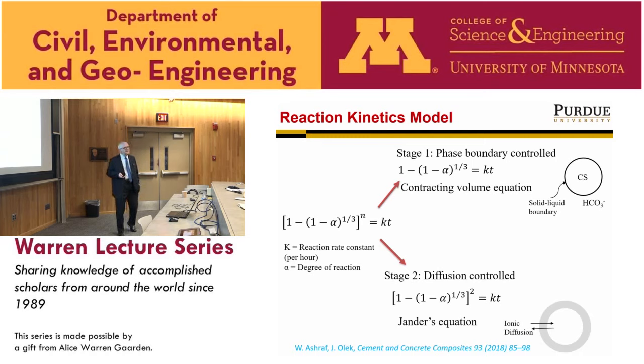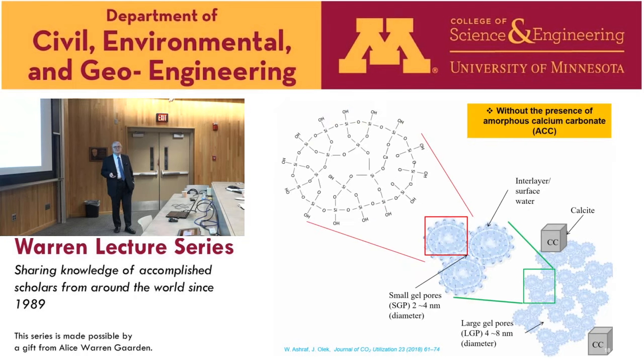So we did some kinetic modeling. We determined the various constants for those processes, and ultimately ended up with a proposed model on nanoscale, really, of what the hydration products, or reaction products, I should say, look like. So we discovered that there are some small gel pores in this material. There is a calcium-modified silica gel, and so those are within the clusters itself. Then the clusters are getting together, and there are larger gel pores between the clusters, and dispersing that, you have those crystals of calcium carbonate that is the main binding phase.